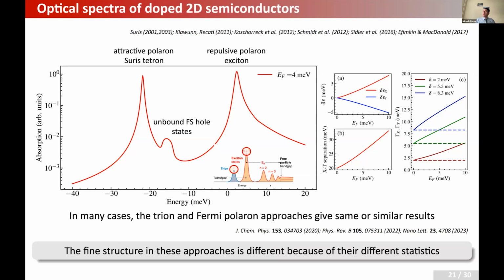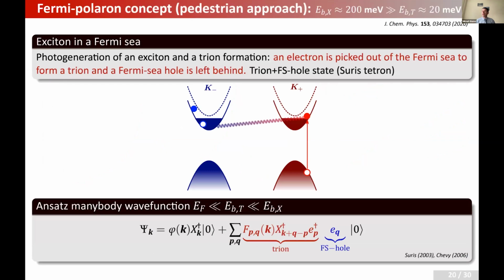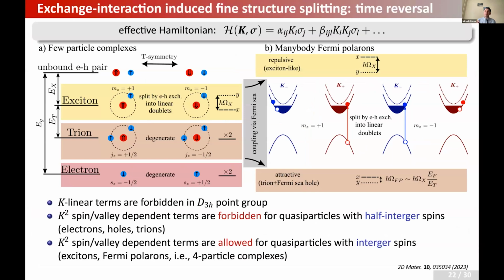The point is that we wanted to find a situation where these two approaches, the Fermi-polaron approach and the trion approach, would give different results. And it turned out that it is possible if we start studying the fine structure of these complexes. Because you see, the Fermi-polaron, or the Suris tetron, is actually a four-particle object. It has an exciton, and it has another exciton, another electron-hole pair. So it has an integer spin. On the other hand, the trion is just a three-particle complex. You have just three fermions here, exciton plus extra electron, and it has a half-integer spin. And these states are very different in terms of the symmetry related to the time reversal.